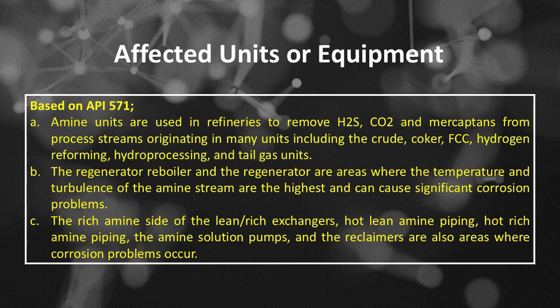Number B, the regenerator reboiler and the regenerator are areas where the temperature and turbulence of the amine stream are the highest and can cause significant corrosion problems. Number C, the rich amine side of the lean/rich exchangers, hot lean amine piping, hot rich amine piping, the amine solution pumps, and the reclaimers are also areas where corrosion problems occur.